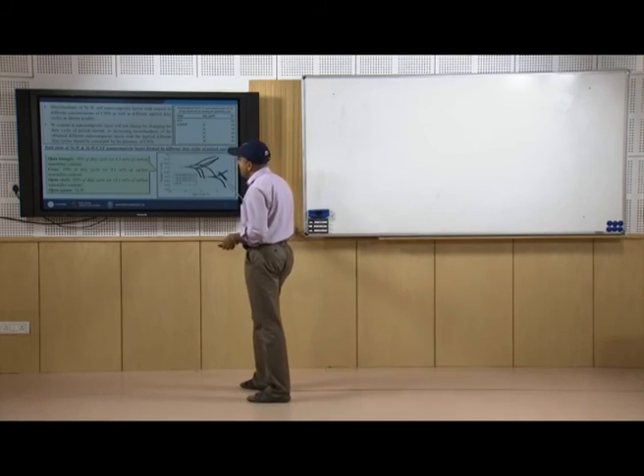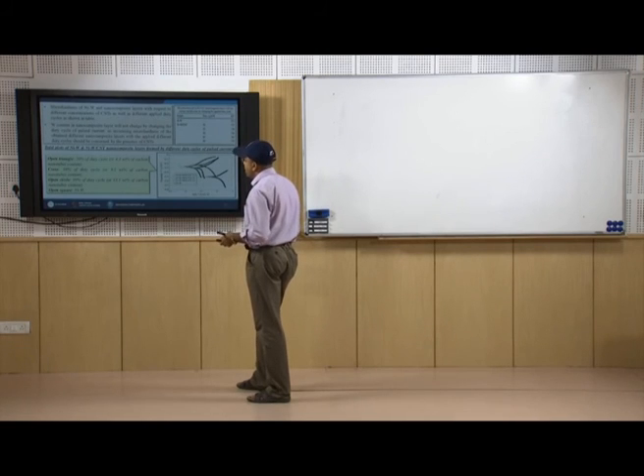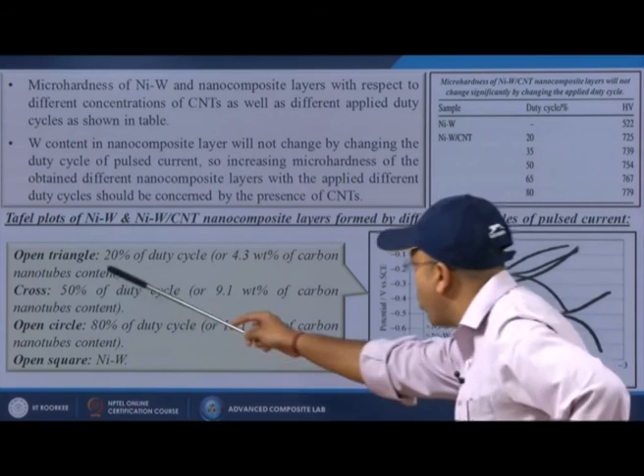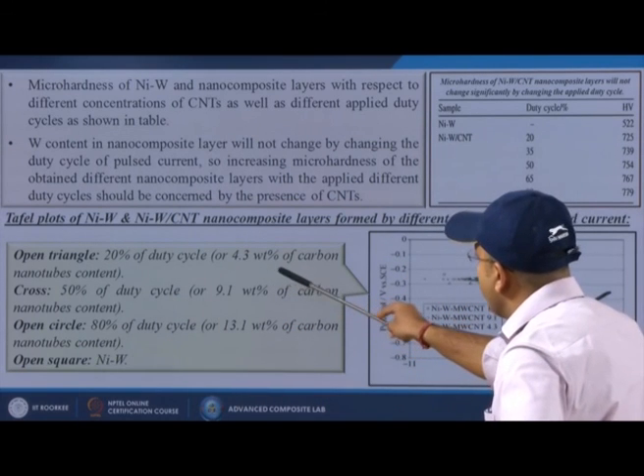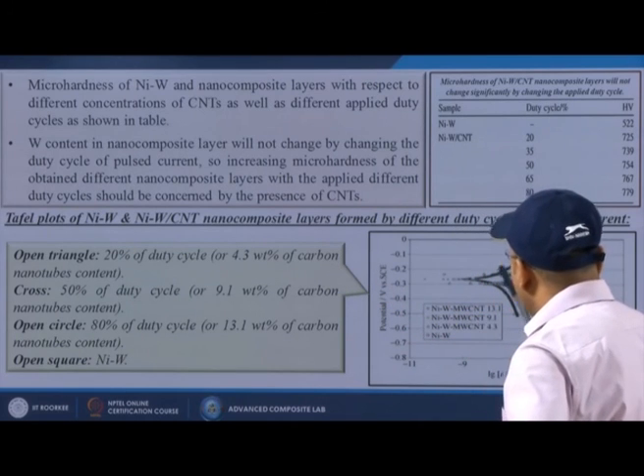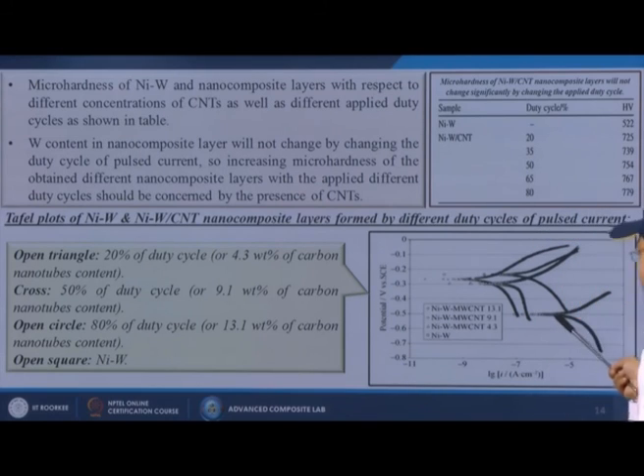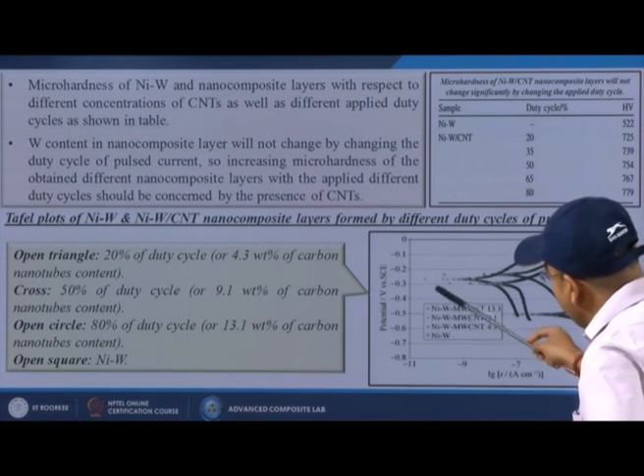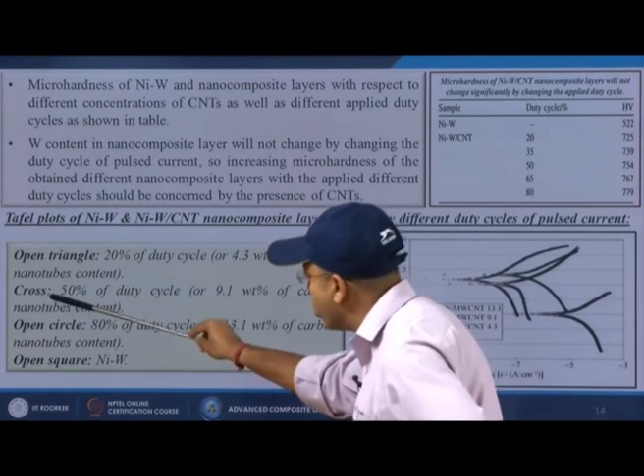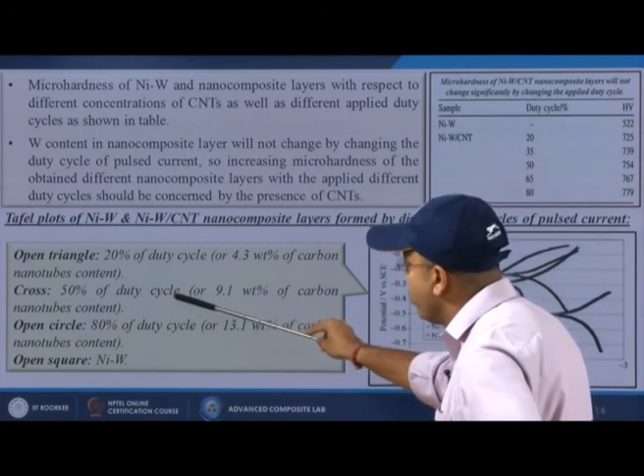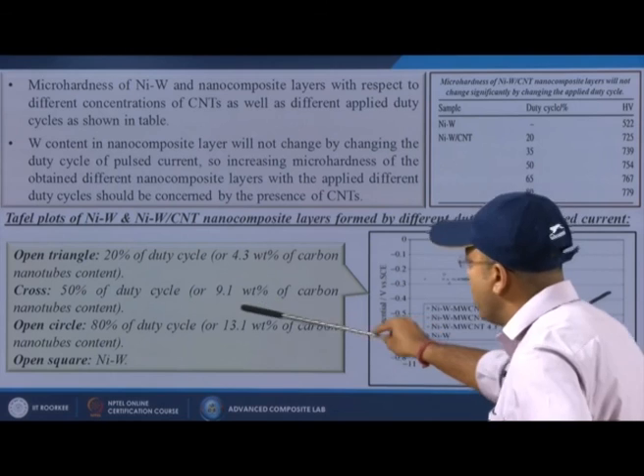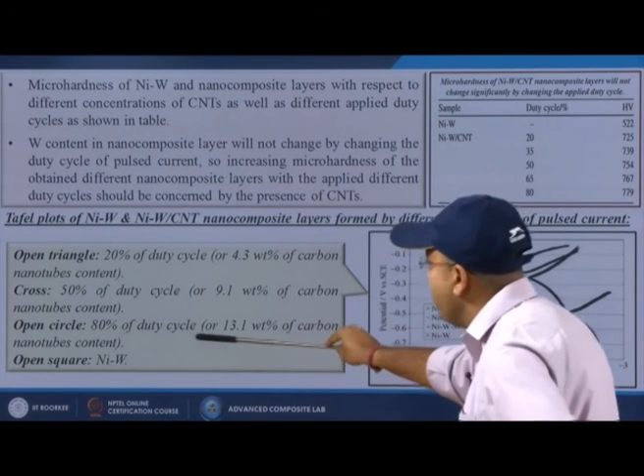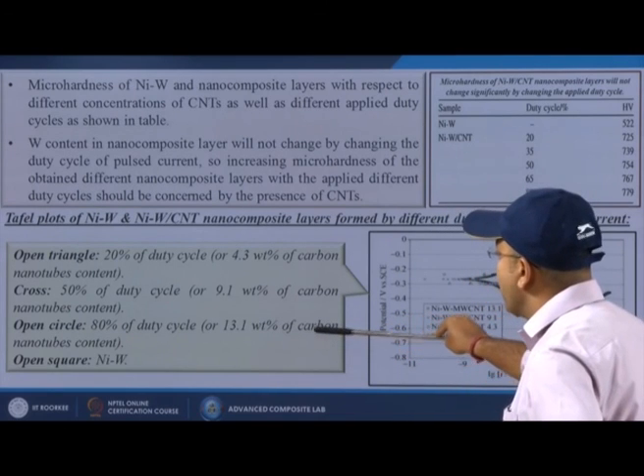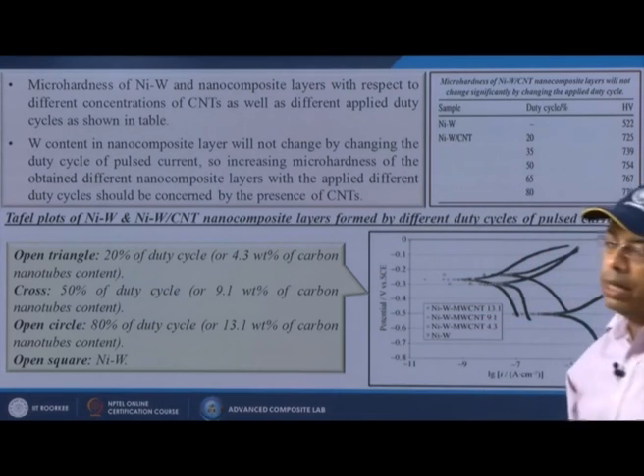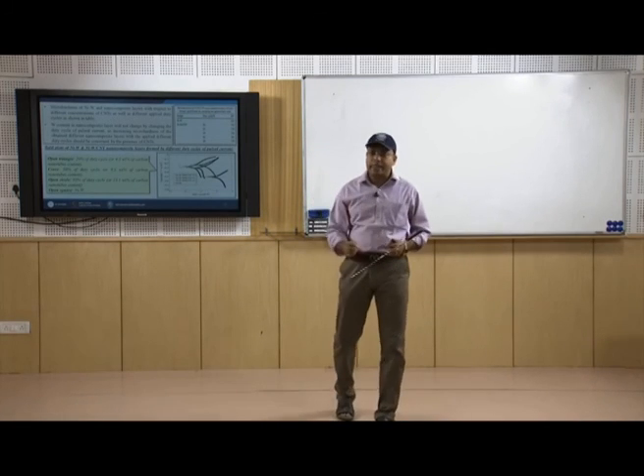Here we are also showing Tafel plots of nickel tungsten and nickel tungsten CNT nanocomposite layers formed by different duty cycles of the pulsed current. When we are talking about the open triangles, the open triangles are the 20% duty cycle or 4.3 wt% of carbon nanotubes content. Here we have shown 4 different graphs or samples, but it is not easily visible. That is why it is written that the cross means the 50% duty cycle or 9.1 weight percent of carbon nanotubes content. The open circle is the 80% duty cycle, which means 13.1 weight percent of carbon nanotubes content, and the open square is only the simple nickel and tungsten composite without the carbon nanotubes.